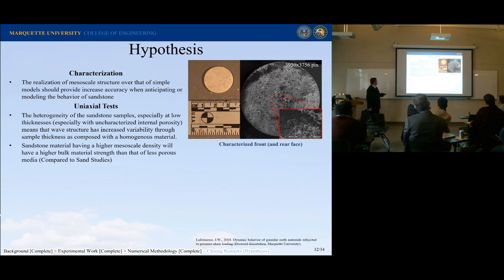Uniaxial tests. I want to see the heterogeneity of the sandstone samples, especially at low thicknesses. This is important because I'm trying to measure the strength of sandstone, not the strength of quartz or the strength of the pores. So I need to make sure that I have a maximum thickness of sandstone possible while still being able to do my pressure shear experiments. Because if they go too thick, I won't be able to load it up in pressure, then in shear.